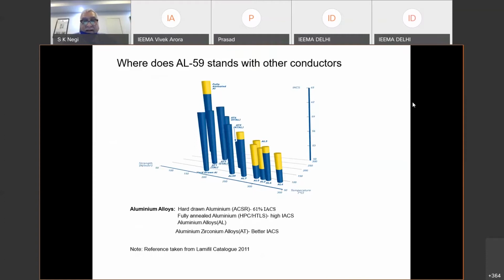To go further into detail in the family of conductors, we will have to see how this AL59 stands. If you see the chart here, this is the hard drawn aluminum, this is the ACSR, and this is fully annealed. Then there are high performance conductors, the HTLS conductors, which actually have a carbon core or other materials, fabrics in that core. So this is fully annealed aluminum over them as an outer layer.